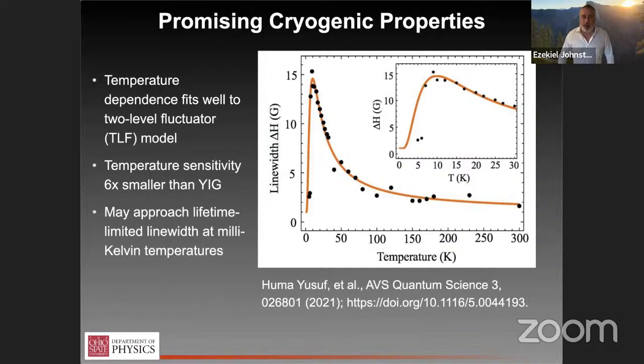And again, for people who may have been following the magnonics literature, a significant challenge to working with YIG in quantum applications is that YIG exhibits the same behavior, only about 6 times larger amplitude in terms of the line width broadening. And so this orange curve is a theory developed for those YIG studies, where what people eventually appreciated is that what we're seeing here is scattering between the magnons and paramagnetic impurities in the system. And so I'll give a quick hand-waving explanation. For the full version, I encourage you to look at the paper here. Our theory collaborators have worked this out in detail.